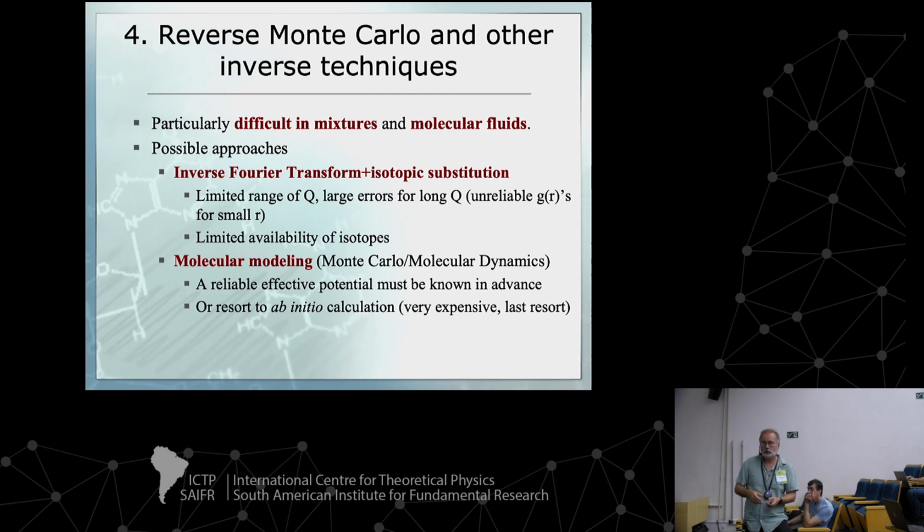And to implement them in ab initio calculations, you have to resort to corrections. So there are a set of corrections, like Grimme corrections, that are relatively good, but they are still kind of empirical in a way. So these are some of the problems you have in ab initio. Also, of course, there's a lot of research trying to improve the methods. Still, it's very expensive, computationally speaking. Getting up to 1,000 molecules is very, very costly. So it's the last resort.